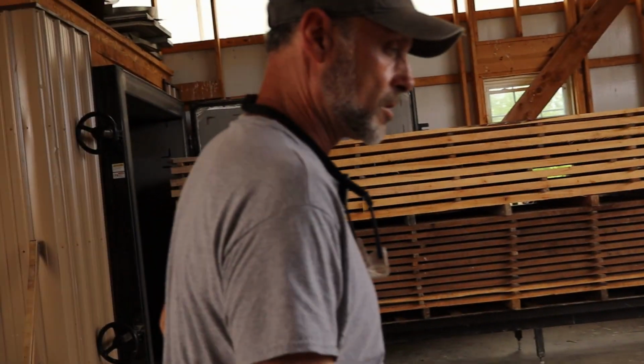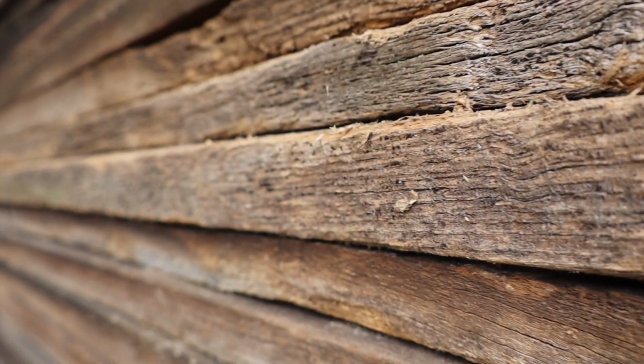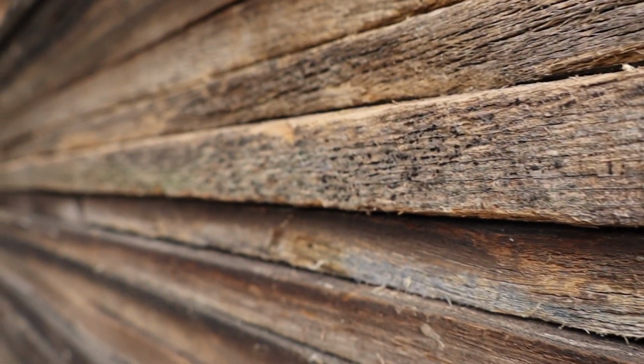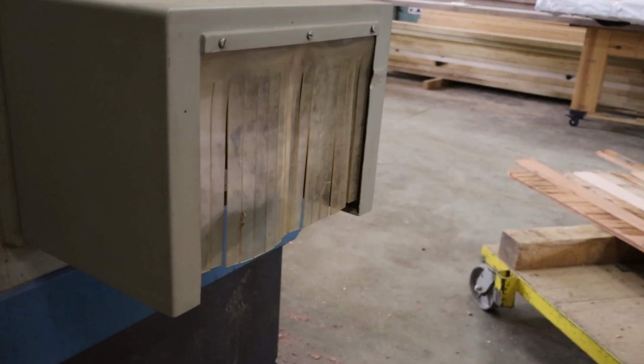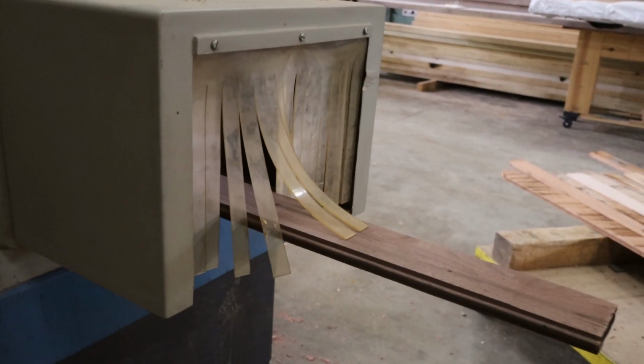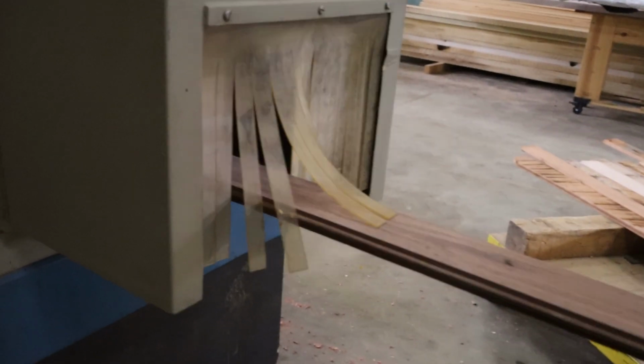So we use a vacuum kiln because of the speed by which I can dry green lumber. I can take it right off the sawmill if need be and put it in the kiln and get it dried. Well, I have people come in all the time. They say, well, this has been air dried for 10 years. It should be okay. And it is usable material, but you still have problems with cracking and splitting because of core moisture that hasn't been expelled in the lumber.